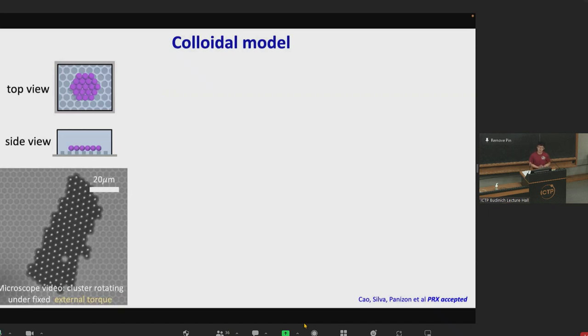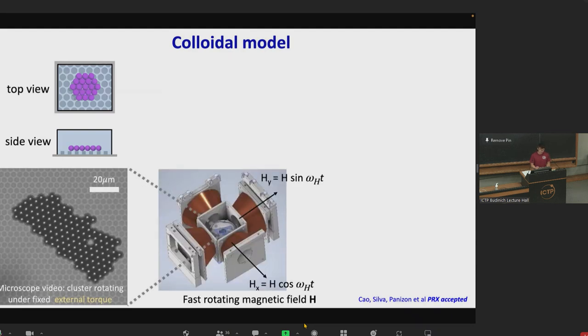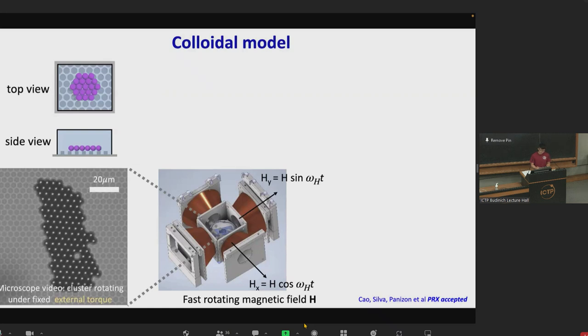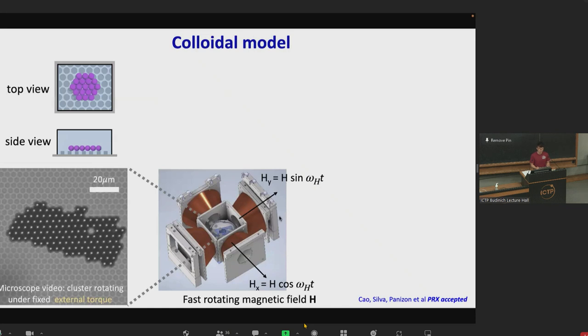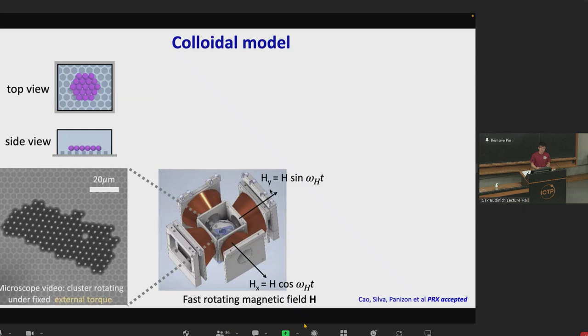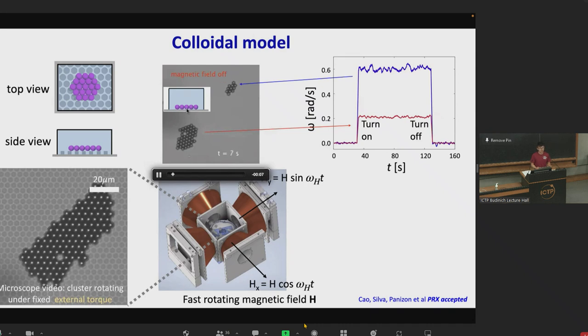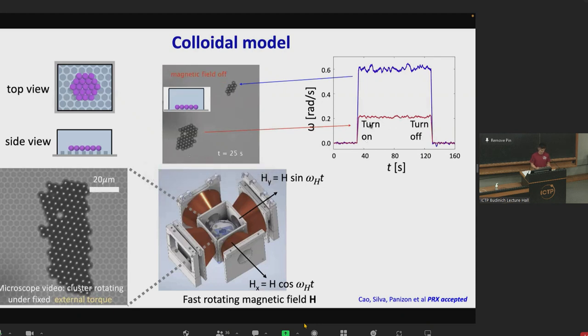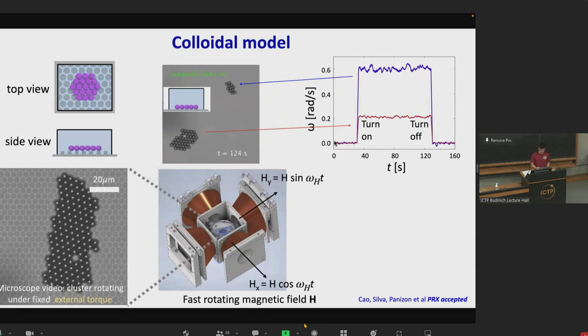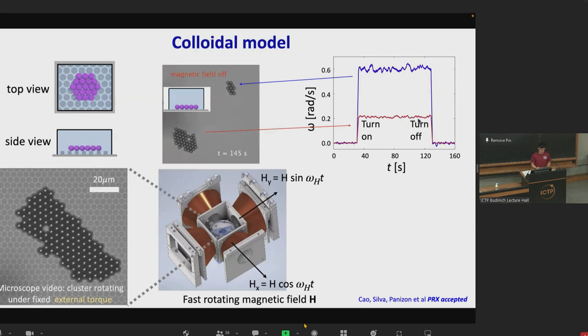Now coming back to rotational friction. The way we realize rotational motion is to apply a constant torque, achieved by a very fast rotating magnetic field in the sample plane, with the help of two pairs of magnetic coils which generate a magnetic field in the X and Y directions with a phase shift of 90 degrees. When this magnetic field is applied to colloidal crystals rotating on a surface without corrugation, the clusters rotate very smoothly with a constant velocity. When the magnetic field is turned off, the rotational velocity goes to zero; when turned on, it reaches a constant value; and when turned off again, it immediately returns to zero.